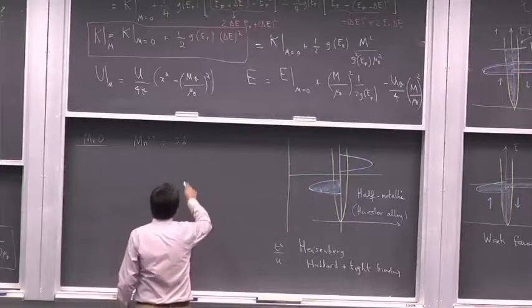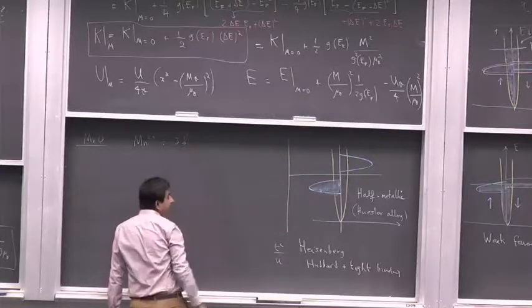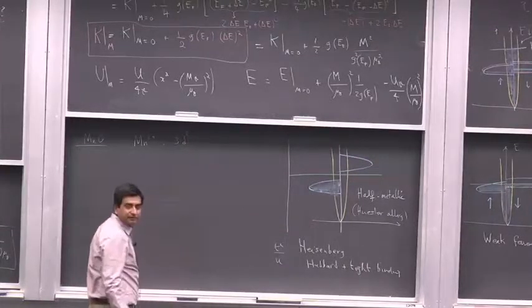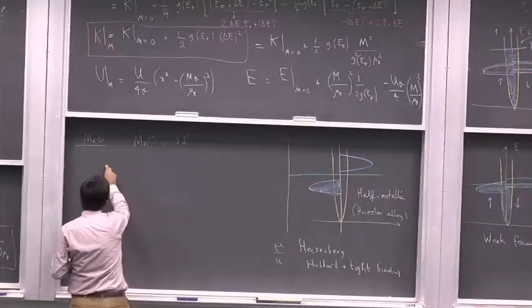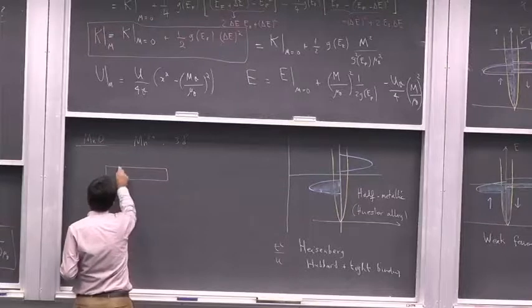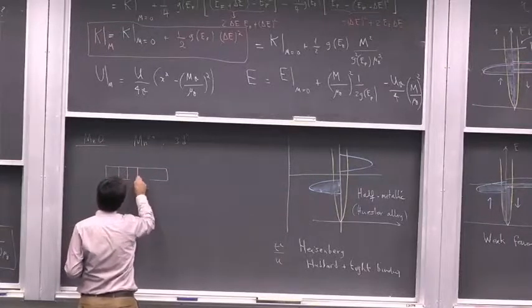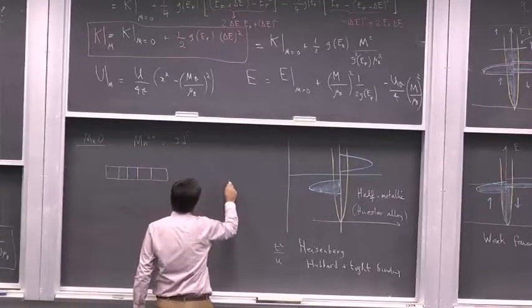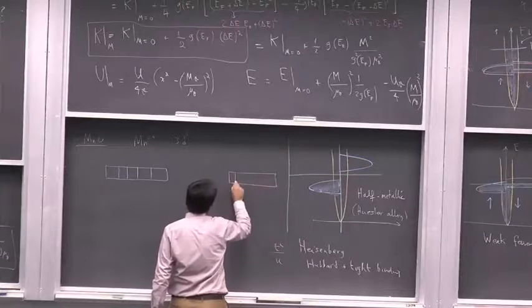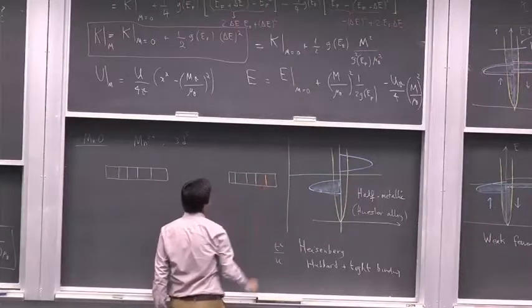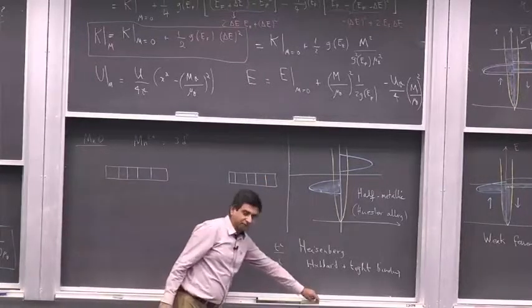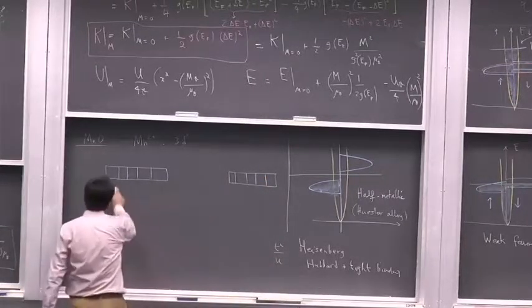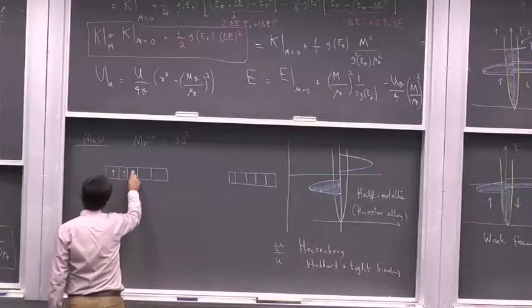Mn2+ is good. It's isoelectronic with ferric Fe3+. So now you have manganese oxide in which you have a manganese atom with 5 d orbitals: 1, 2, 3, 4, 5. In each of these orbitals there is one electron. They must be parallel because of Hund's rule.